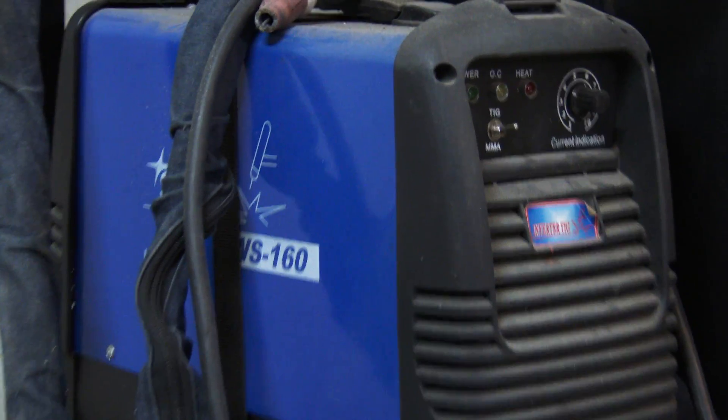Alternatively I could have bought a MIG welder. TIG welders can run in DC mode, which is great for welding steel where 70% of the heat is going into the job and 30% into your handpiece. When welding aluminium you need to run some reverse polarity, and that current flowing in the opposite direction strips the oxide layer off the aluminium. But unfortunately now you have 70% of the heat going into your handpiece and 30% into your job.